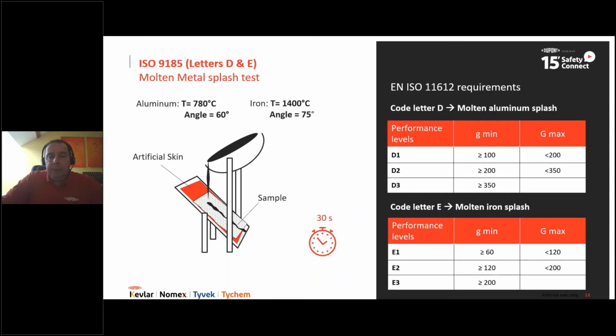So you're checking if this artificial skin is sustaining any damage or not after having been exposed during 30 seconds or a predefined quantity of molten metal. Now, this is a pass-fail test, and you always start at the lowest level. For example, at the molten aluminium splash, at the performance level D1, you take 100 grams of molten aluminium that you're pouring on your fabric, on your Nomex, for example, and you wait for 30 seconds, and then you're checking if your artificial skin has been damaged or not. If it's not damaged, you pass already the level D1.